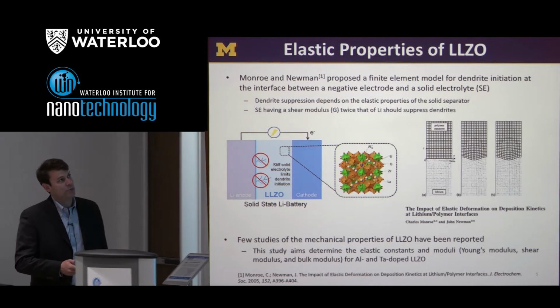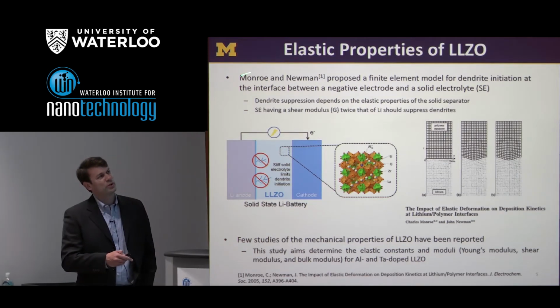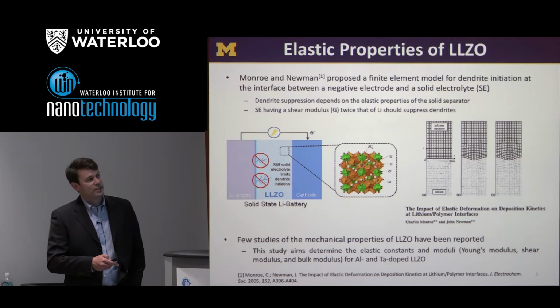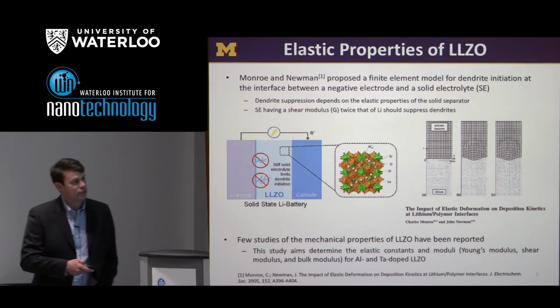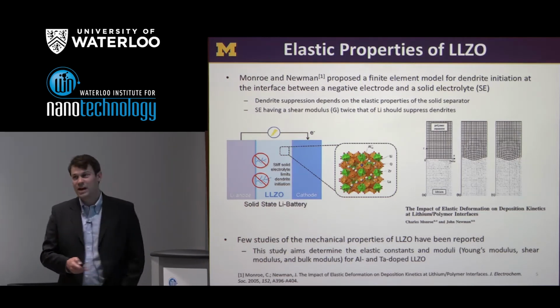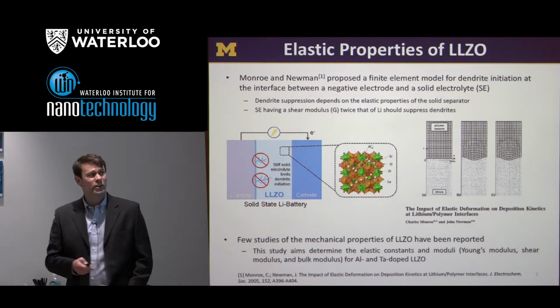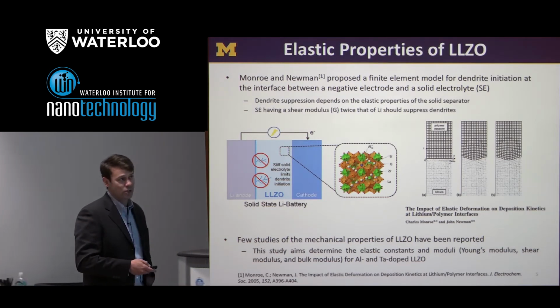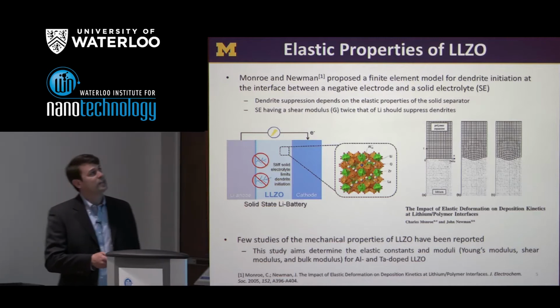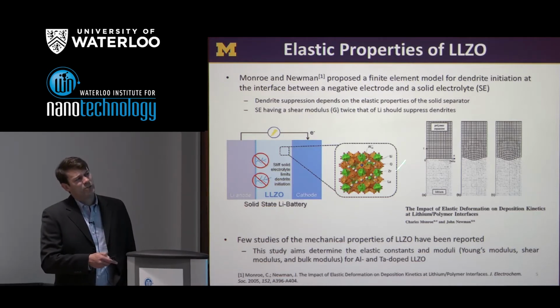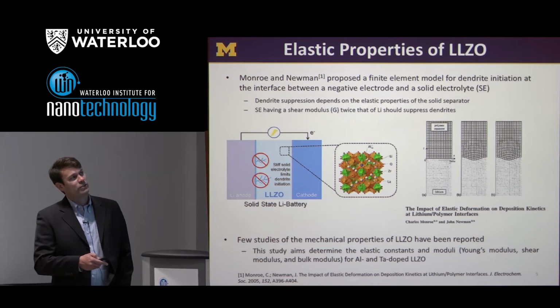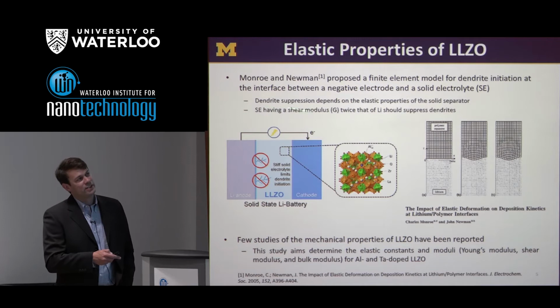Starting there, I want to go back to a model proposed by Monroe and Newman. About 12 years ago, Chuck Monroe and John Newman started to think about what properties would be needed for a viable solid electrolyte. At that time, they were mostly focused on polymers, which can be rather soft. They developed a finite element model, which you can see here, based on linear elasticity. What they concluded from that model was that dendrites can be suppressed if we have a solid separator which is sufficiently stiff, and that is quantified by looking at the shear modulus of the solid electrolyte.